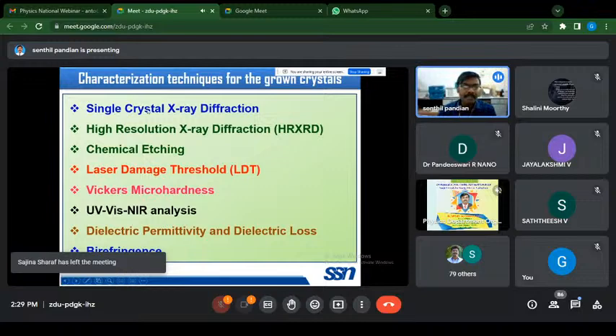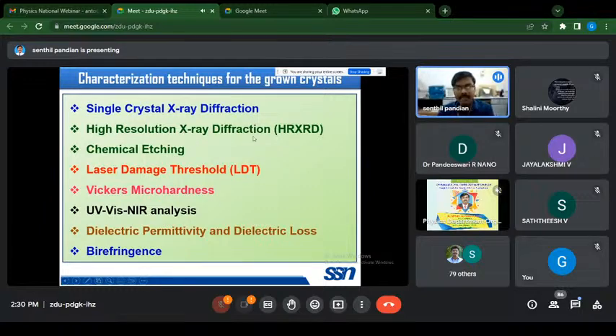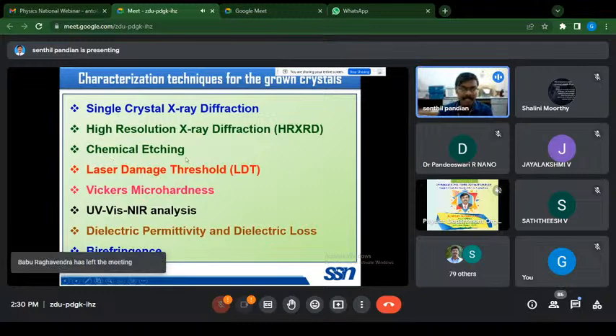First, we carried out single crystal X-ray diffraction measurement in order to confirm the grown crystal, and to check the crystalline perfection of the grown crystals, we carried out high resolution X-ray diffraction measurement. And in order to identify the etch pit density of the grown crystal, we selected chemical etching.